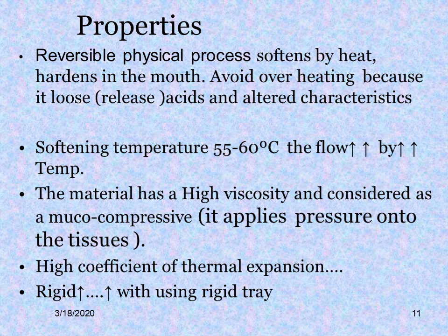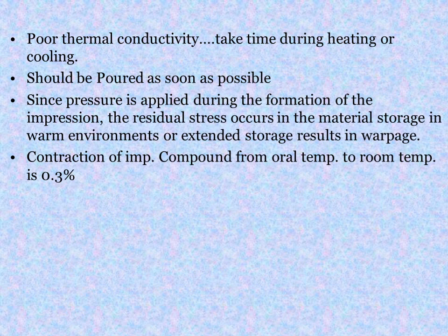High coefficient of thermal expansion. The rigidity increases with using a rigid tray. Poor thermal conductivity. Takes time during heating or cooling. Should be poured as soon as possible. Since pressure is applied during formation of the impression, residual stress occurs in the material. Storage in a warm environment or extended storage results in warpage. Contraction of impression compound from oral temperature to room temperature is 0.3%.